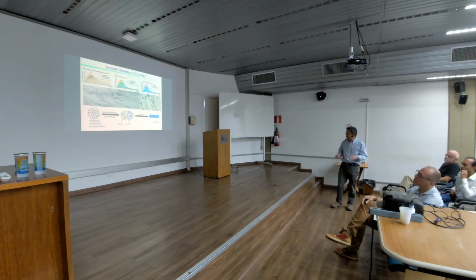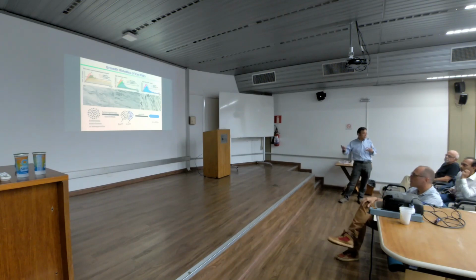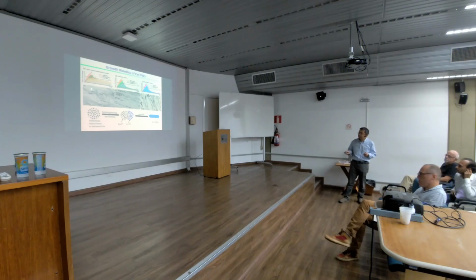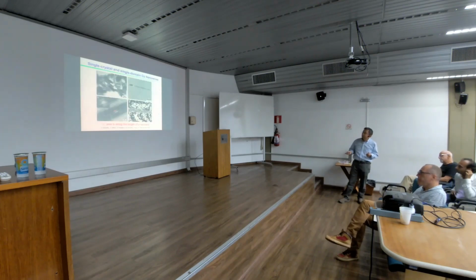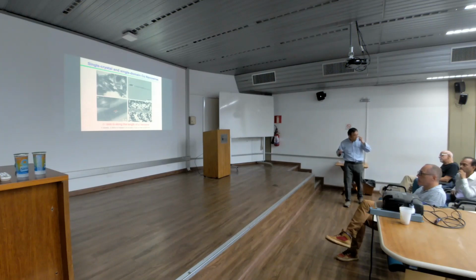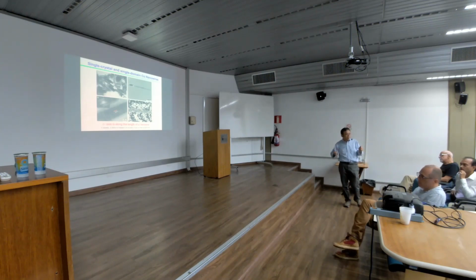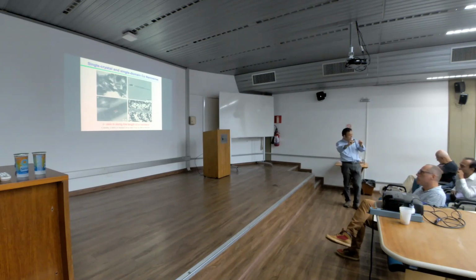Then we tried, as I mentioned, the nanowire approach again. We could control the aspect ratio, morphology, and size. Finally, we were able to produce homogeneous cobalt-based nanowires. You see the single crystal, single domain, two singles. That's important. Why? Because Brown's theorem assumption is very clear: your magnets must be absolutely homogeneous.